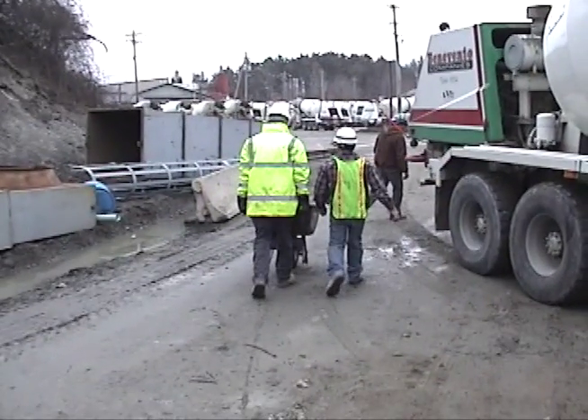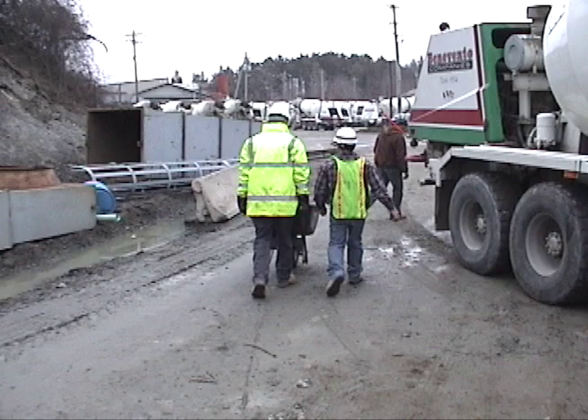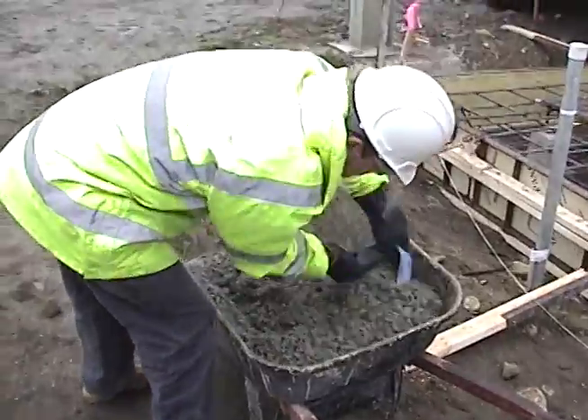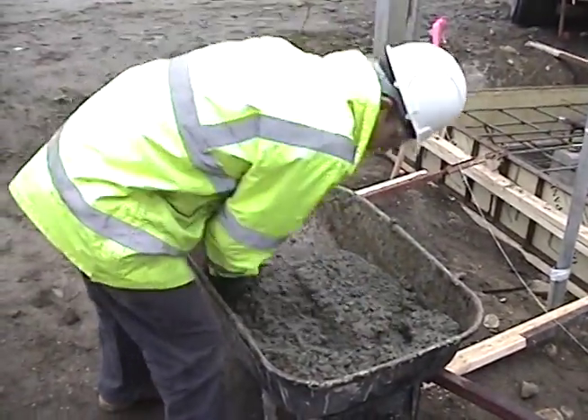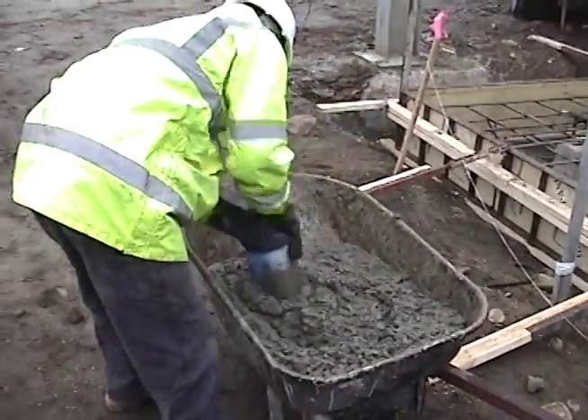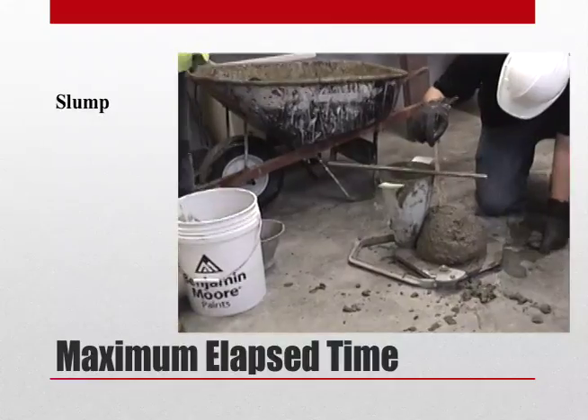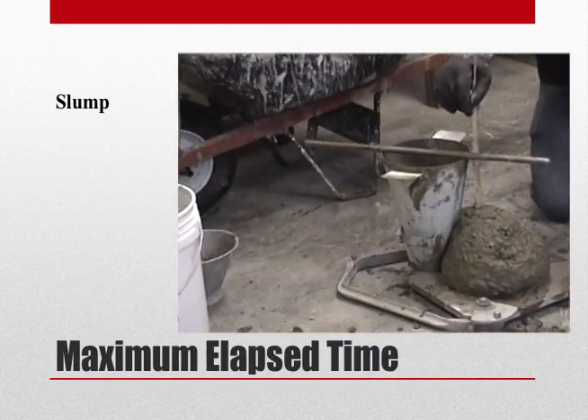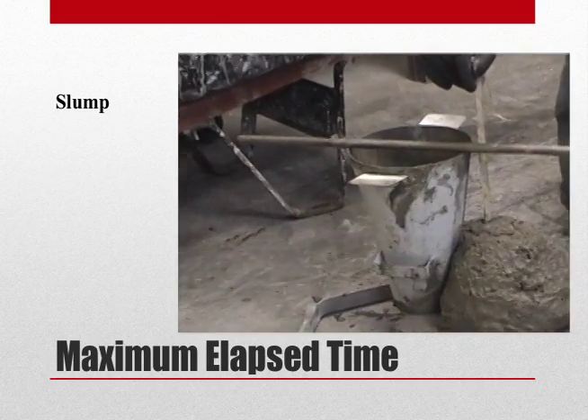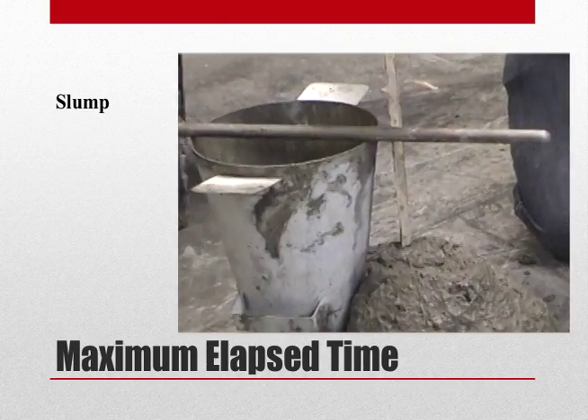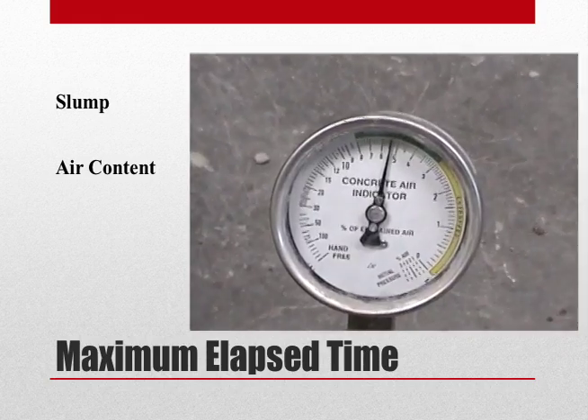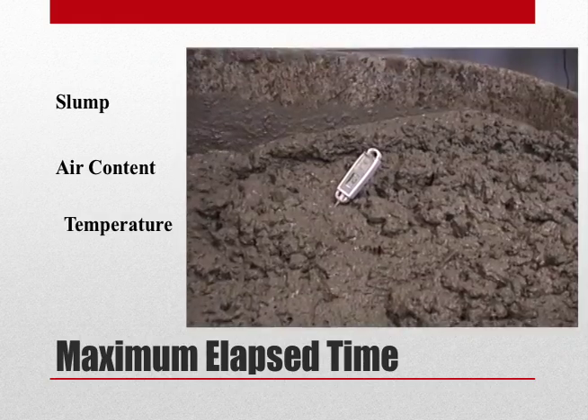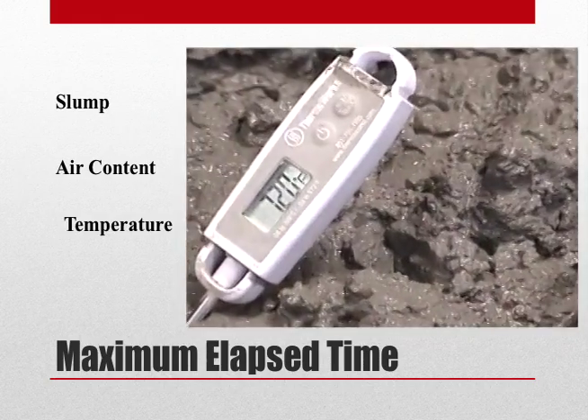Furthermore, we want to transport our sample as short a distance as possible to the testing site. Before beginning any tests, we must thoroughly remix our sample. Remember, the maximum elapsed time between obtaining your sample and beginning the tests is 15 minutes.